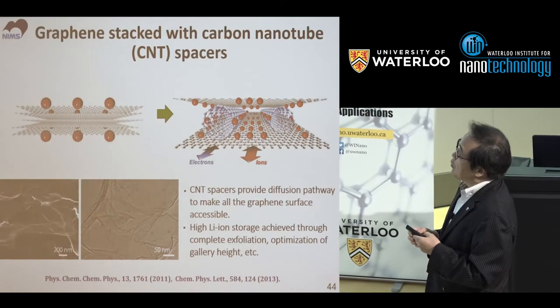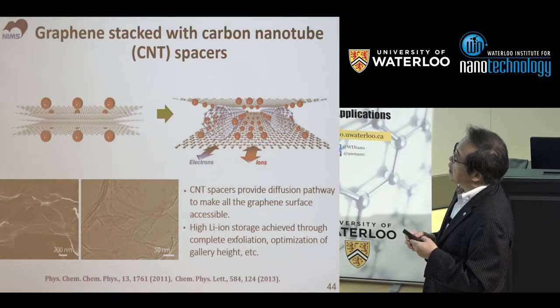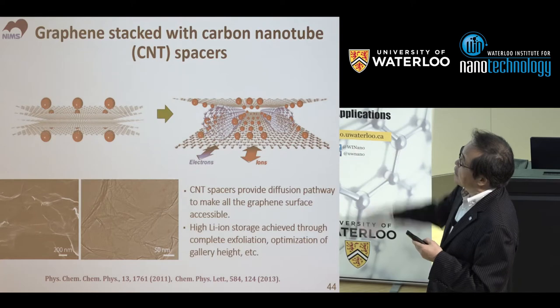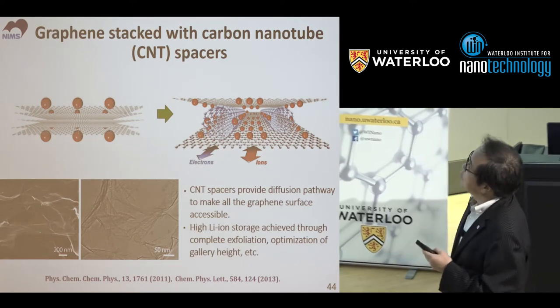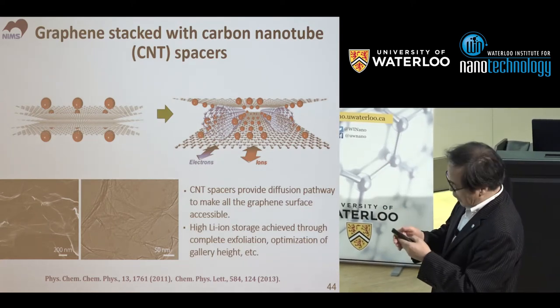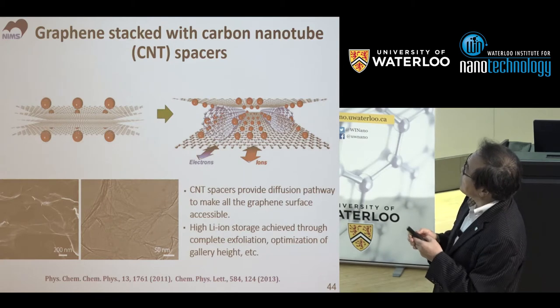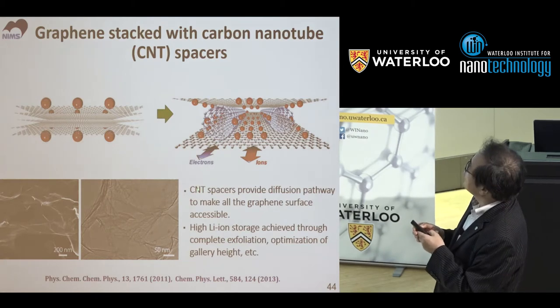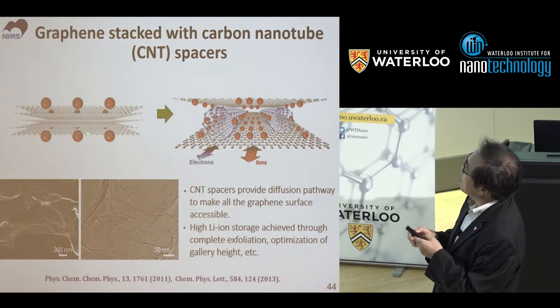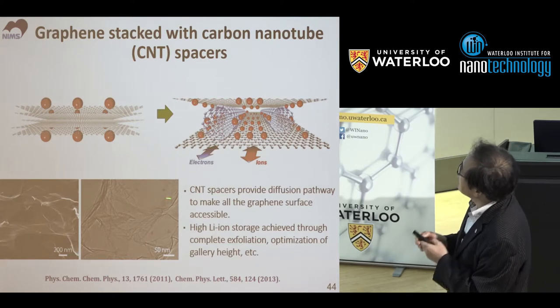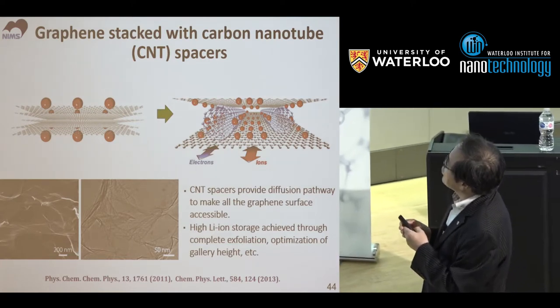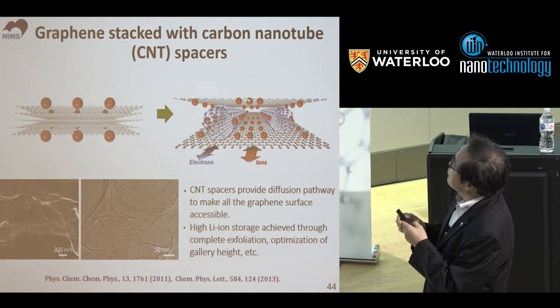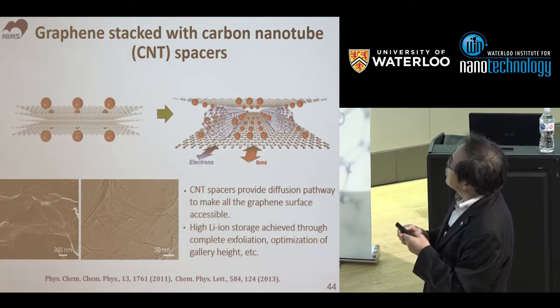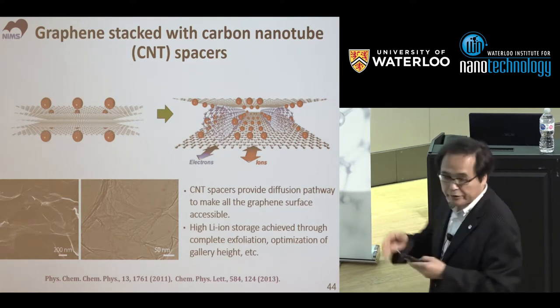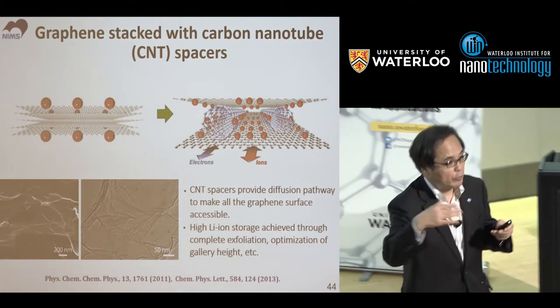The first example, which was developed in this lab, is graphene stacked with CNT spacers. In this case, carbon nanotubes were used as a spacer for graphene. Then the diffusion pathway can be made. This diffusion pathway makes all the graphene surface accessible to lithium ions, for example.